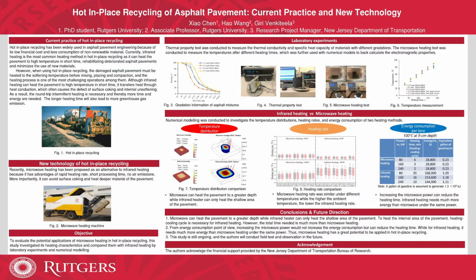In terms of the energy consumption, the microwave heating time was found proportional to the power. So the energy consumption under different powers for microwave is the same. But for the infrared heating, the total energy consumption would decrease gradually when the power increases. And under the same heating power, the energy and time needed for infrared heating is much more than microwave heating. So overall,